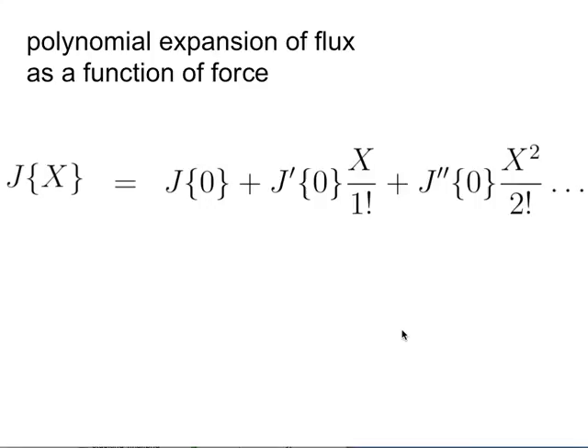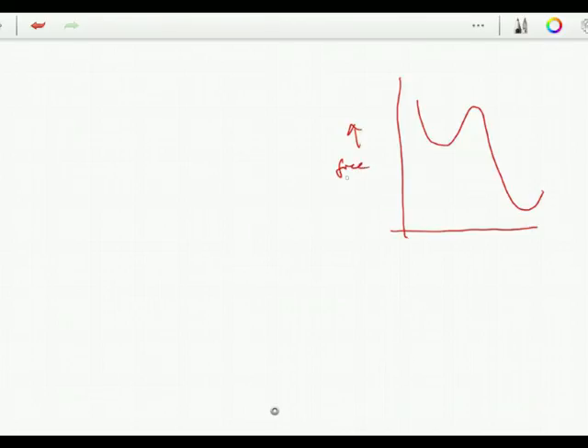Now, have you come across this previously? Let's consider a case where the flux is not proportional to the force, but becomes proportional to the force when the force is small. The case in hand is about an interface, and the rate of interface movement is controlled by the transfer of atoms across an activation barrier. So we are plotting free energy on this axis and a coordinate along here, and this is A and this is the position B. This is the driving force, delta G, for atoms to jump from the left to the right, and this is the activation barrier, Q.